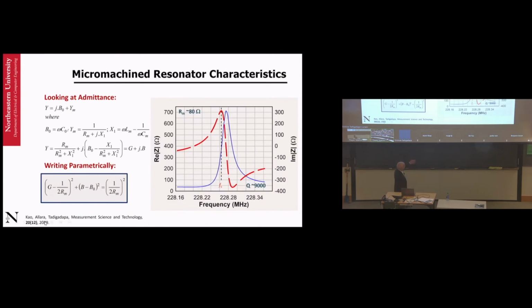So we fabricate it. Just to let you know, this is a 228 megahertz resonator. To get to 228 megahertz, we're looking at 6 microns of quartz in thickness, okay? So that means if I started with 100 micron quartz, we had to thin it down by 94 microns before we can get to these frequencies. The standard resonators that you can buy in the market will be 300 microns thick, and they're 5 megahertz in frequency. So this type of possibility is because of MEMS etching and microfabrication.